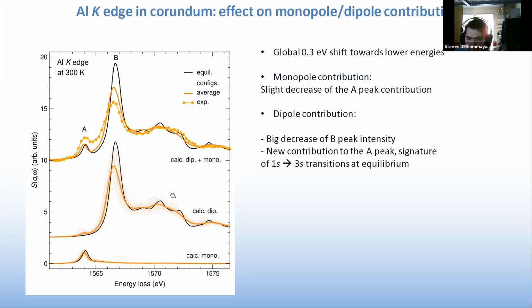And we can see that the effect on the monopole is just a slight decrease of intensity plus the slight shift toward lower energy. But that is general to all contributions. So just for the monopole contribution, the effect is a slight decrease of this peak, the A peak, at least the monopole contribution to the A peak. And for the dipole part, we can see that there is a big decrease of the B peak, as well as the growth of a dipole contribution to the A peak.